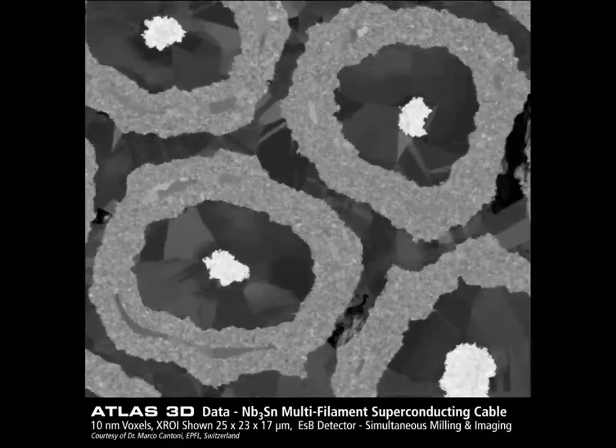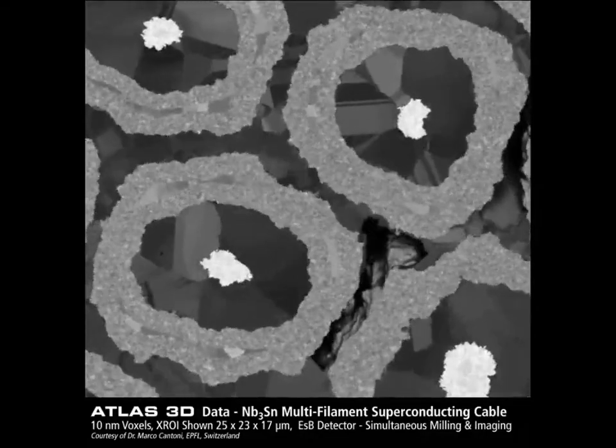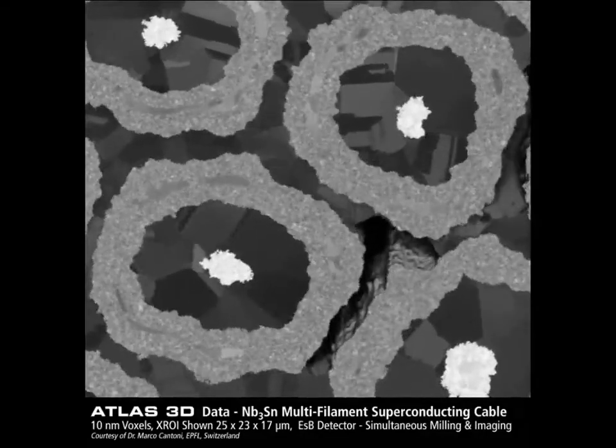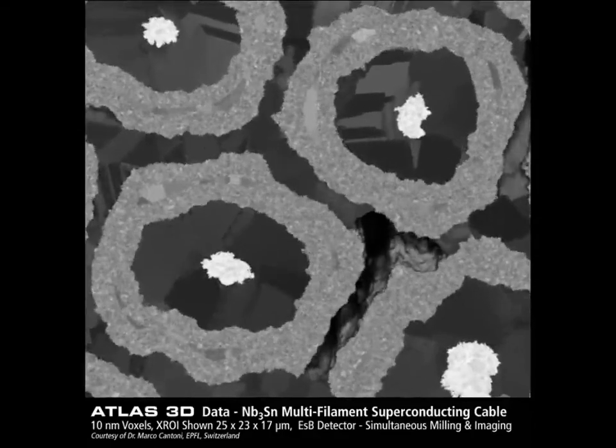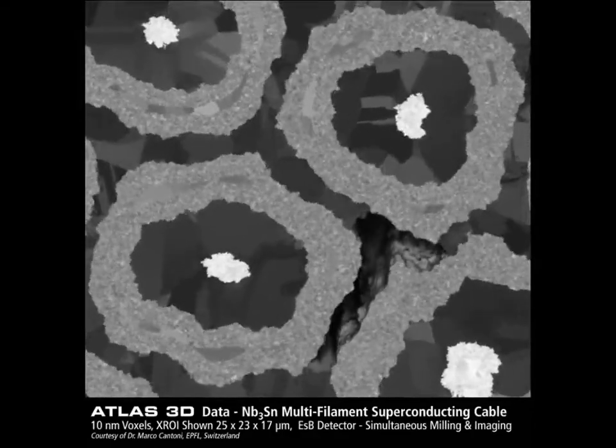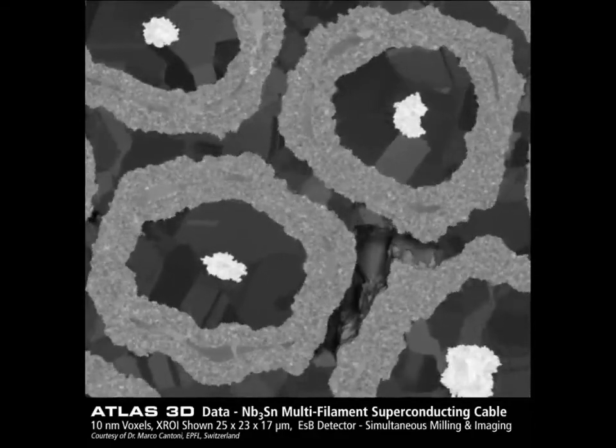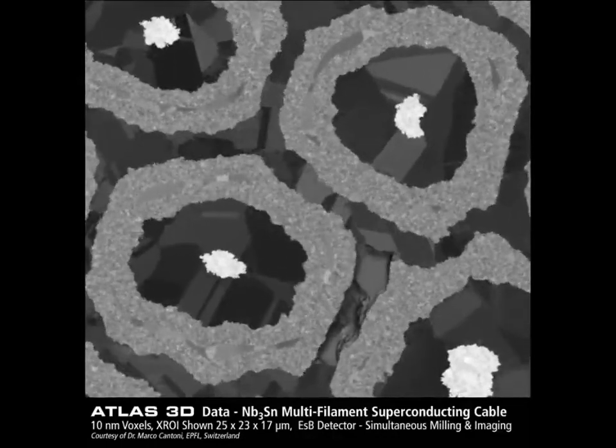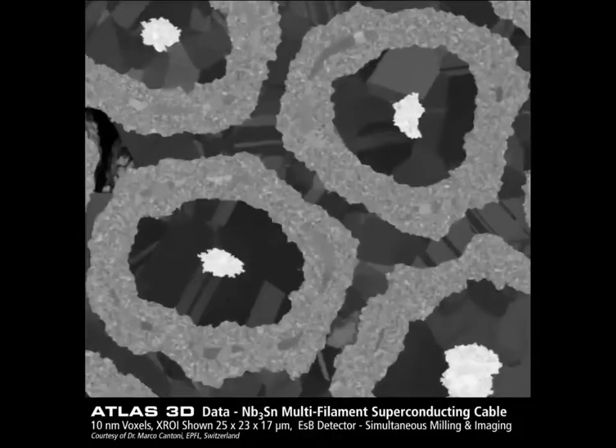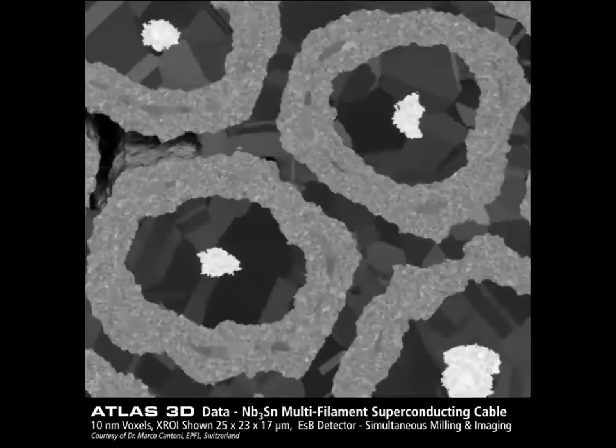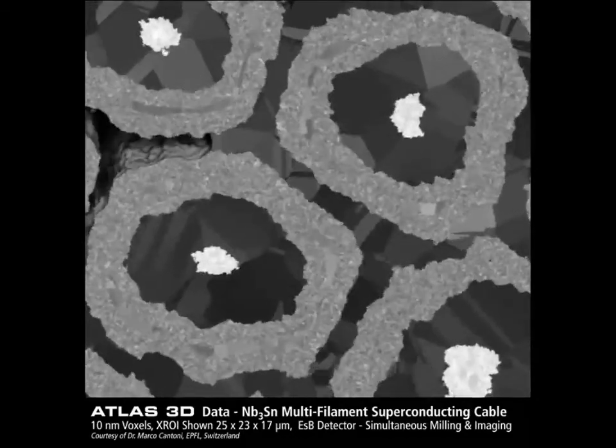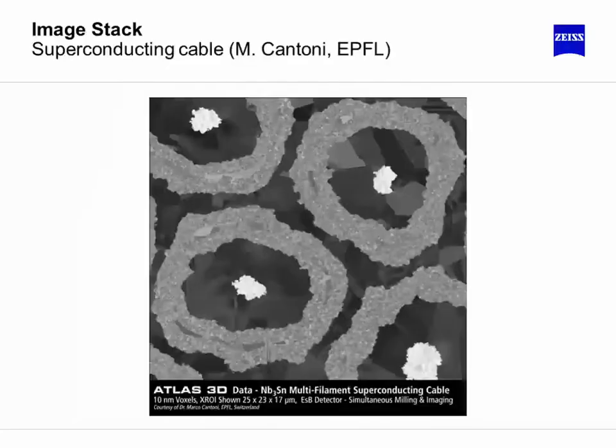The next slide shows you an example of raw data acquired on a niobium-3 tin multifilament superconducting cable. These images were acquired using a backscattered electron detector. You can see the different materials present in the sample, and you can also see the grain structure of some of the phases.